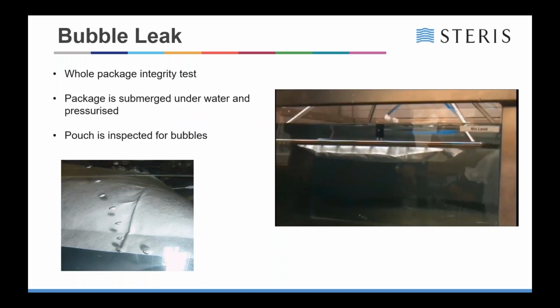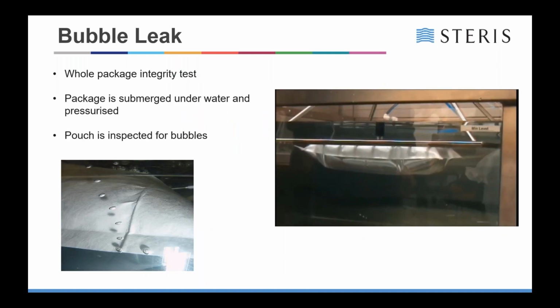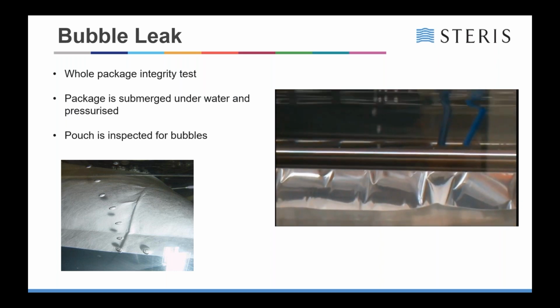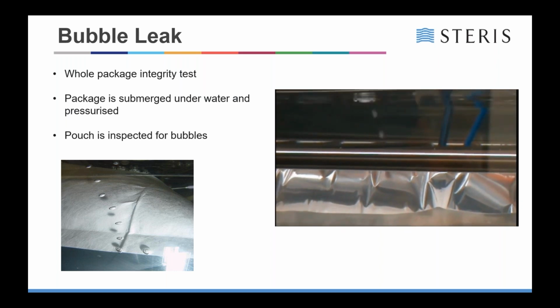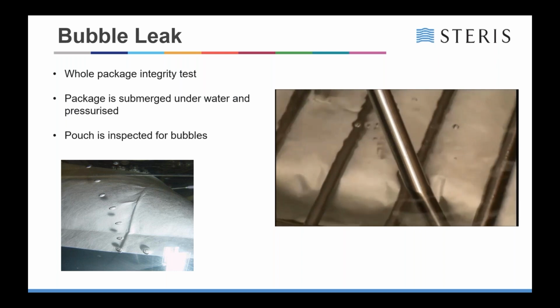Again, it can have issues in that it can show up false positives. If you look at the video that's playing at the moment on screen, you'll see that this is what you're looking for. It's a continuous stream of bubbles out through a defect. But you can also get those continuous streams of bubbles from other areas in the pouch, so you have to be able to distinguish what they are. The very simplest way to do that, if you're getting a continuous stream of bubbles from the likes of a Tyvek or paper pouch, is to rub your finger across the top of it. If they stop momentarily, it's breathing. If it doesn't stop, it's more than likely a defect.